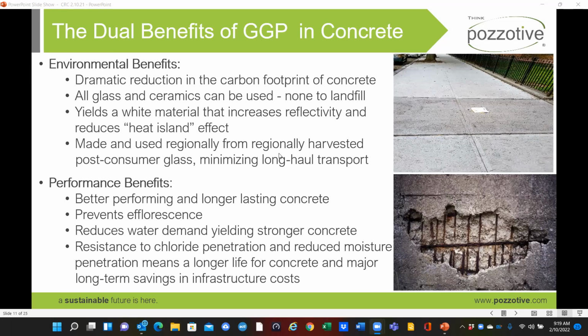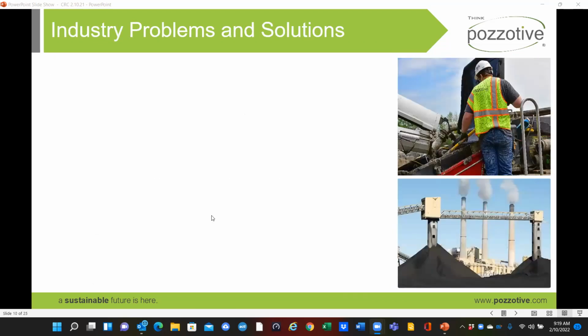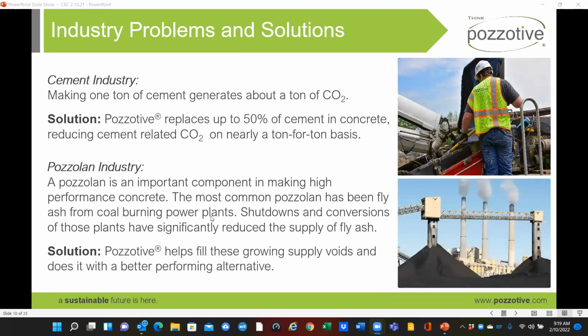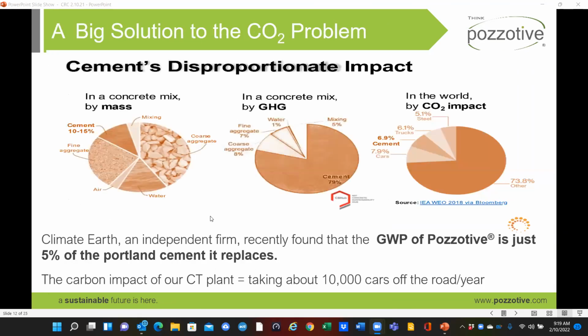I've got some slides here. I won't take too much time because of our limited time today, but it basically creates a better performing, longer lasting concrete. It prevents efflorescence, the white powder you're seeing coming out of concrete sometimes. It uses less water, which means a stronger concrete. But the big thing it does, it reduces chloride penetration, the bad impact that our road salts have on our concrete. When salt and moisture get into our concrete, that photograph happens on the right. And that's why our state DOTs are excited about having a better pozzolan to use.